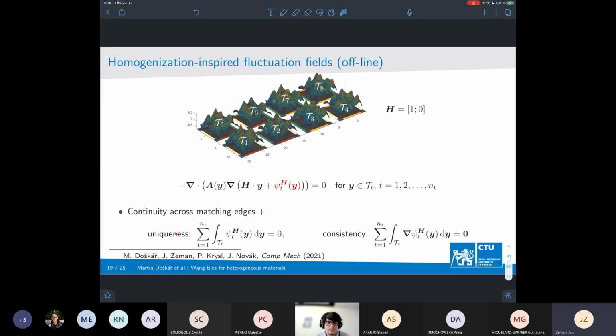And we also need to ensure some additional conditions on this enriching field in order to get uniqueness. So we need to fix the zero mean, basically, or some constant value. And we also require some additional consistency in order to prevent this additional contribution for preventing these linear variations. So these are the underlying ideas. How this is done is explained in this publication, which appeared very recently.